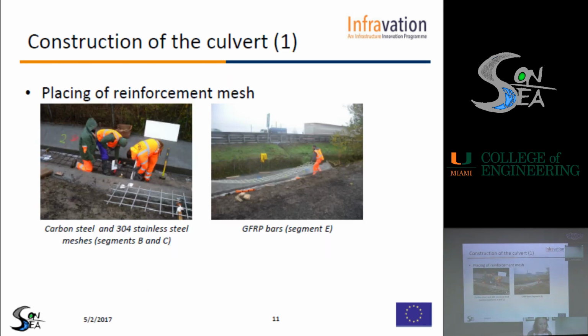These are some of the stages of the construction of the slab. The rebars were assembled in the form of a mesh on site, and they were placed at the bottom of the slab. The side walls had been cast a day in advance compared to the slab. Then we installed the probes that, as you can see from these photographs, were fixed to the reinforcement so that they were exactly at the same depth.